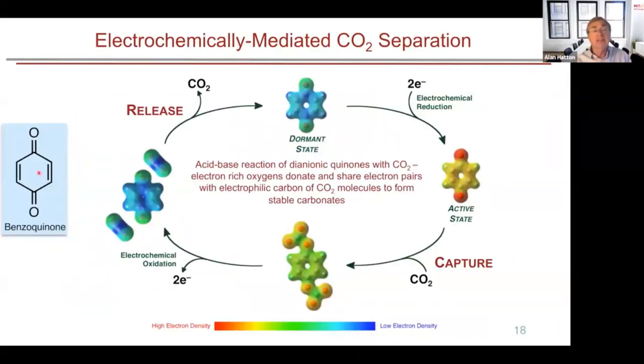But in this particular case, let's think about the quinone systems in general, as shown here. Typically, these in the dormant state have no capacity for CO2. They're just pretty inactive. We can then, if we go through electrochemical reduction, add a couple of electrons to this guy. What you'll find is the electrons accumulate on the oxygens here. We've got various high electronic densities associated with this, which makes it a very active state for the capture of electrophiles such as CO2, which will form the dicarbonate as shown in this case.